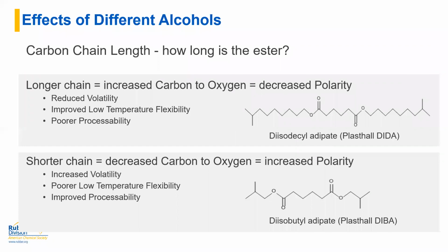So those were the different acids. What can we do with alcohols when we're reacting with those acids to give these ester groups? The first thing that we can look at is carbon chain length. This is similar to the acids, but we can adjust the length of our chains coming off of the ester groups in the middle. A longer chain, such as in the DIDA, the diisodecyl adipate there, will give you an increased carbon to oxygen ratio, as we already discussed, decreasing your polarity.